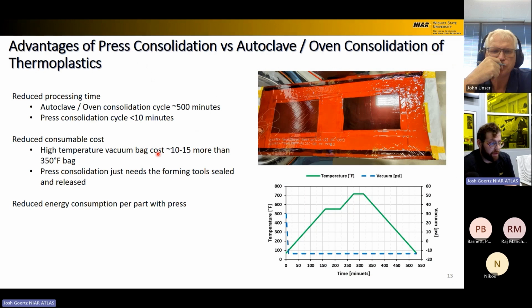Some of the advantages of doing this press consolidation versus autoclave and oven for thermoplastics: cycle time is the big one. Autoclave consolidating your high temperature thermoplastic materials, you only have to maintain the 720 degree temperature for 20 or 30 minutes to get your consolidation properties. But you have to remember there's the entire ramp up and then ramp down of the temperature, so your actual cycle time ends up being quite long despite having the real short dwell.